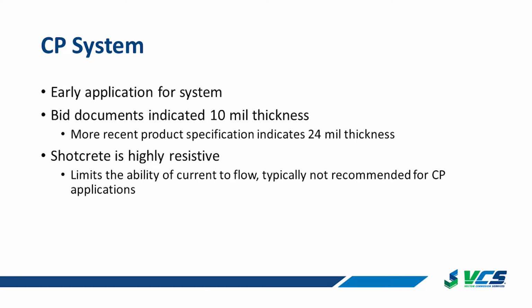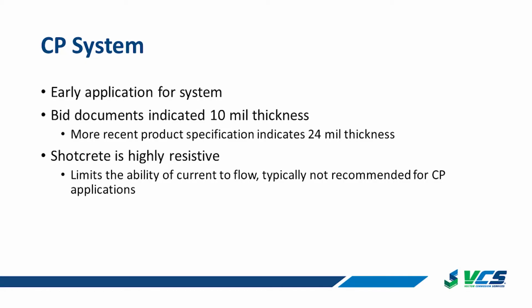Some of the difficulties in this was an early application for this galvanic system. It was one of the early trials for it, so they didn't quite have all the quote-unquote bugs worked out. They only put 10 mil thickness for this coating back in the original bid documents, but specifications for this product nowadays actually call out for 24 mils. So we think that in the early days, they went too low in a trial and then realized that they needed a little bit more thickness for durability. The thickness of this on these 2 piers was lower than probably what should have been, so that probably hurt some of the durability.